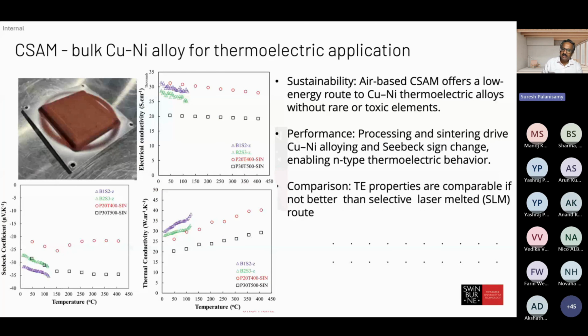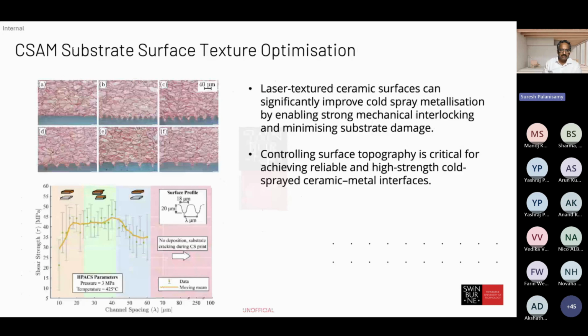Again, we looked at the thermal conductivity point of view, how the properties look, mainly from the sustainability point of view. Air-based cold spray offers a low energy route to copper nickel thermoelectric material. So this one is a copper nickel material here, a combination of copper and nickel together, which we used to try to study whether it gives far better properties than copper alone.